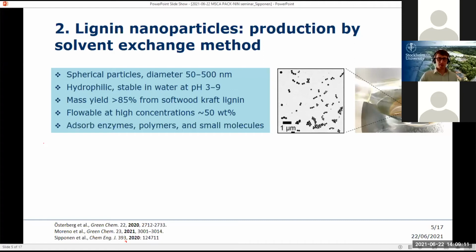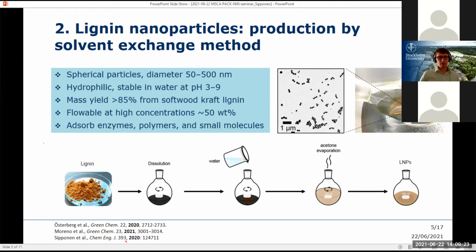As a product, these are very amphiphilic. They are good adsorbents for different materials like enzymes, polymers, and small molecules. The process is in brief just shown here in this schematic. It involves first a dissolution step and then the precipitation by removing the solvent or adding water into the solution. And then finally, of course, the organic solvent can be removed and recycled, and we get the final particulate product.